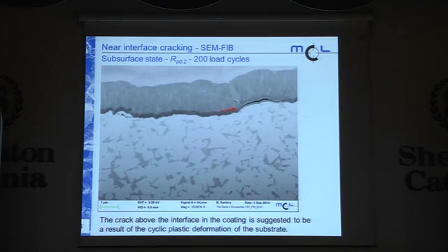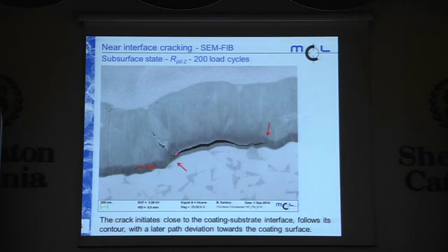This here is, well, an interfacial crack. We cannot really say it's close to the interface within the coating. And it is very similar to the cracks that Mr. Ustinkoff in the laminated materials section showed yesterday. Its maximum opening is in the middle, so it may have originated here, and it goes parallel to the interface of the coating. And if there's an inhomogeneity in the coating, maybe some weak spot, it will deviate eventually. This is, in my eyes, the early stage of the coating delamination, and is very relevant to failure.